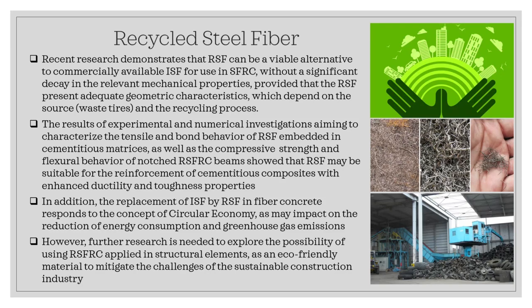The results of experimental and numerical investigations aiming to characterize the tensile and bond behavior of RSF embedded in a cementitious matrix, as well as the compressive strength and flexural behavior of notched recycled steel fiber reinforced concrete beams, show that recycled steel fiber may be suitable for the reinforcement of cementitious composites with enhanced ductility and toughness property. In addition, the replacement of ISF by RSF in fiber reinforced concrete responds to the concept of the circular economy, as it may impact the reduction of energy consumption and greenhouse gas emissions.